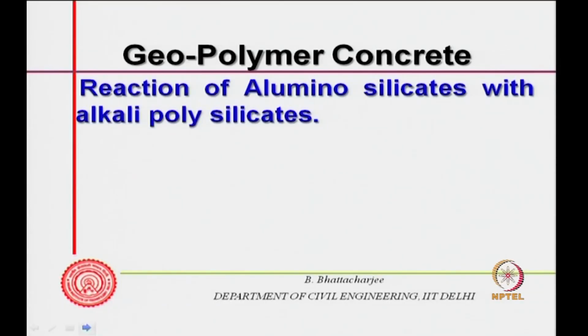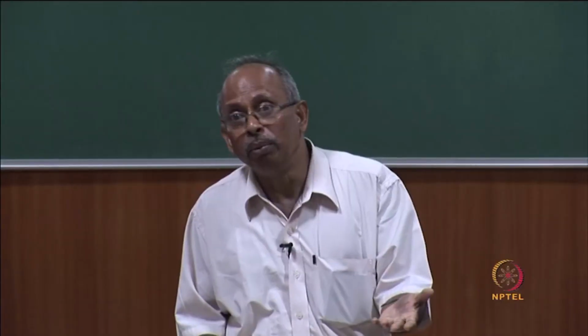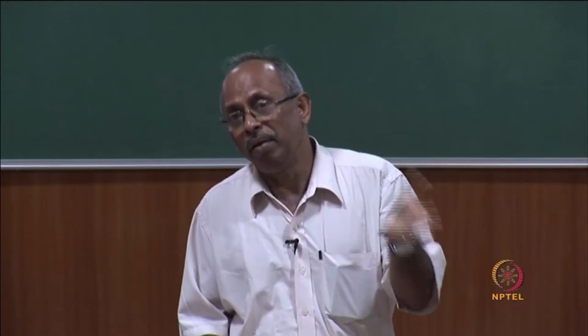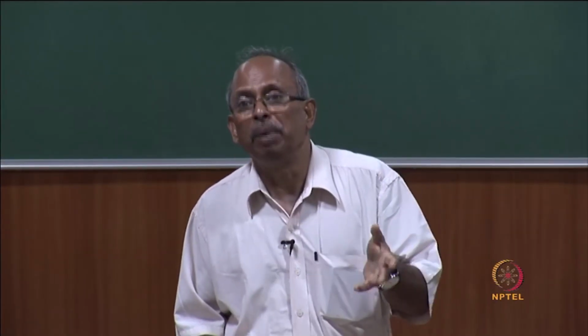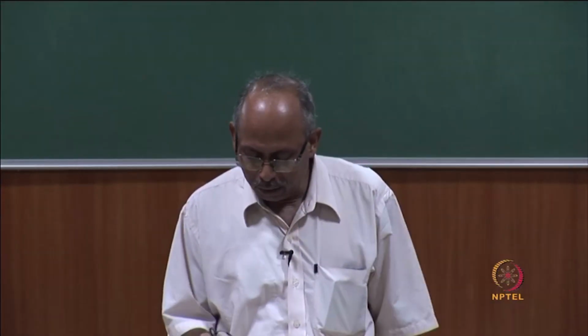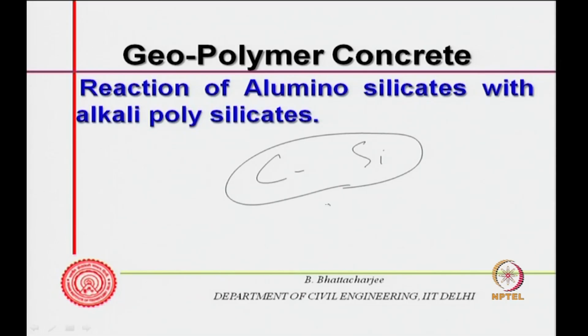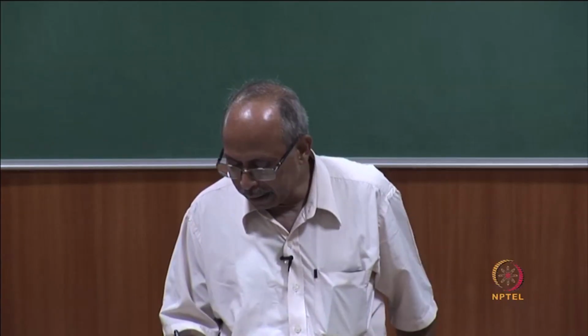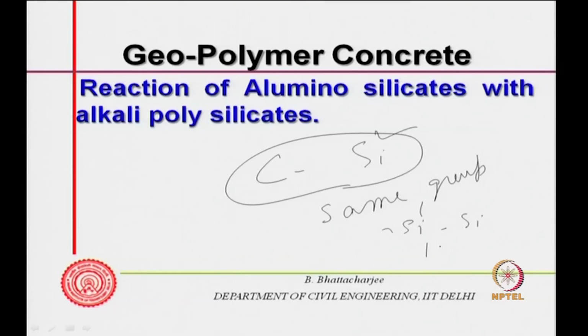Then there is another concrete of a similar kind called geopolymer concrete. Now, this does not use cement at all. That was high volume fly ash, less cement, but now no cement, fully fly ash. Basically, carbon and silicon belong to the same group in the periodic table. Therefore, silicon also shows a polymerization tendency. It can form a bond with silicon, Si-O-Si bond possible, 4 valencies. So, it can show similar properties as carbon. So, it can be polymerized to a limited extent.